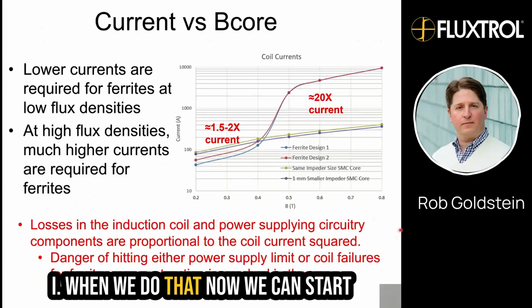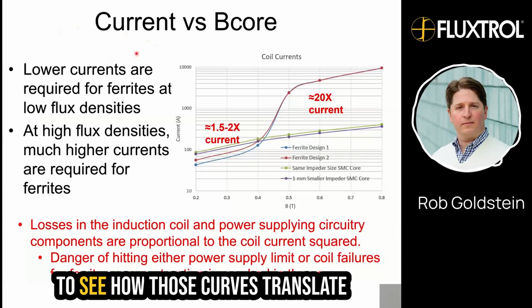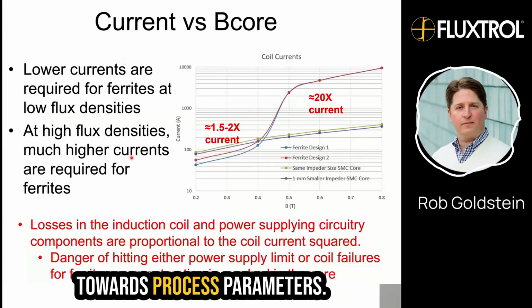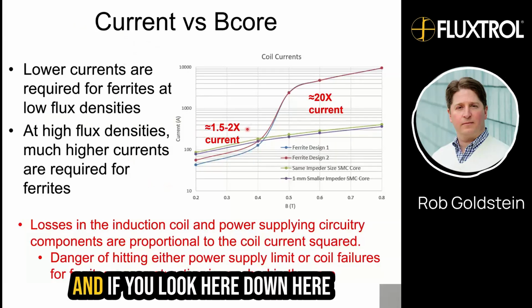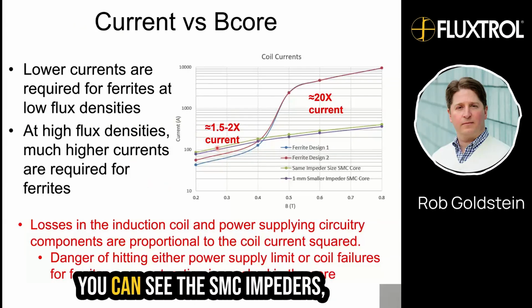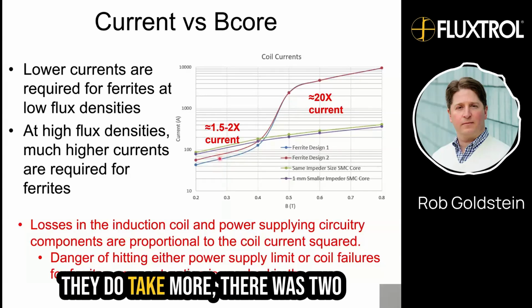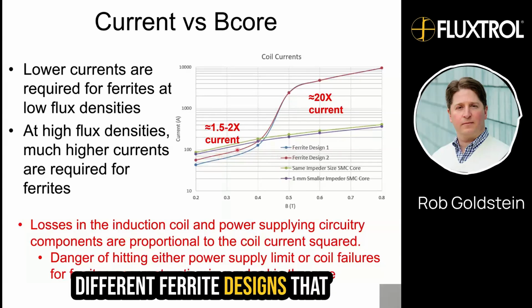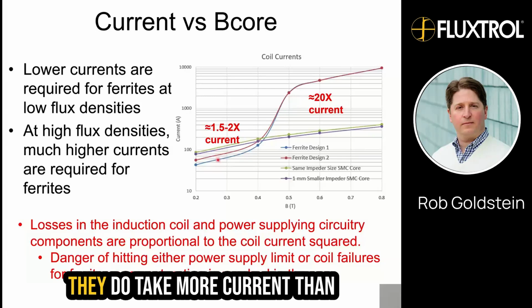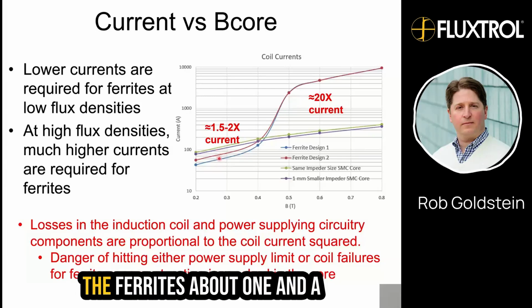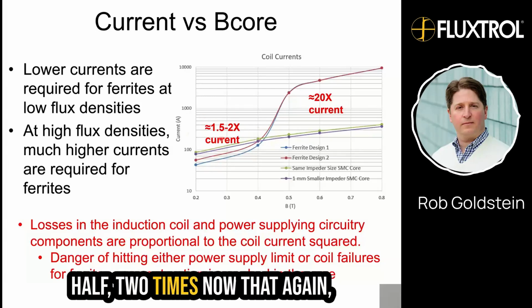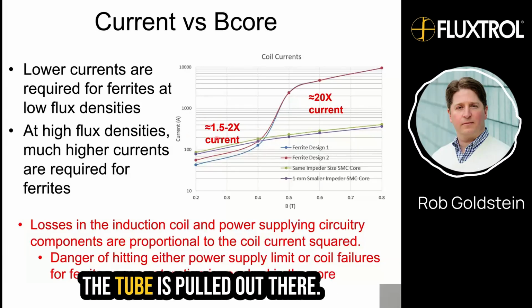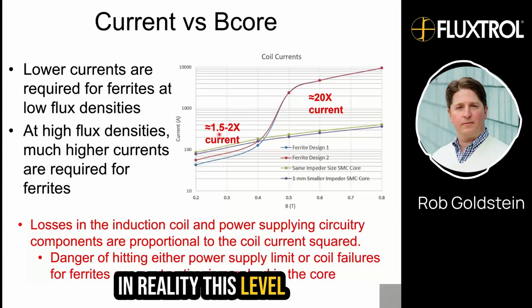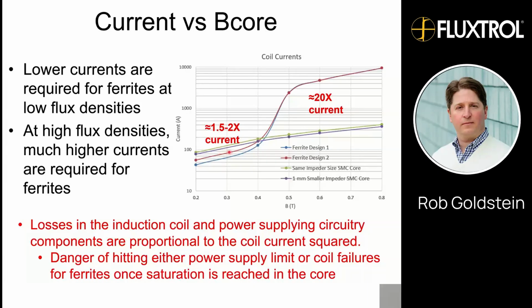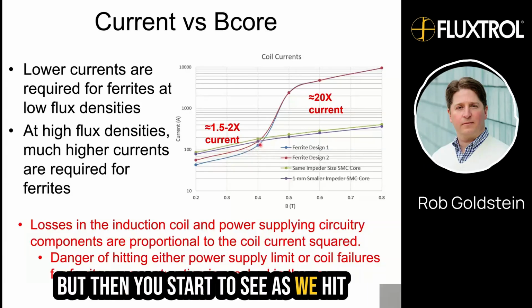When we do that, we can start to see how those curves translate towards process parameters. If you look down here, you can see the SMC impeders. There were two different ferrite designs being compared as well. The SMC impeders do take more current than the ferrites, about 1.5 to 2 times. Again, the tube is pulled out of there; in reality, this level will be much smaller. But then you start to see it as we hit that wall.